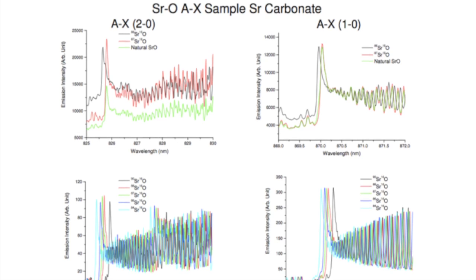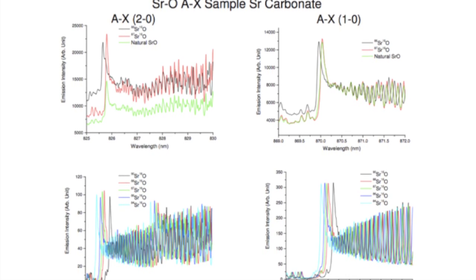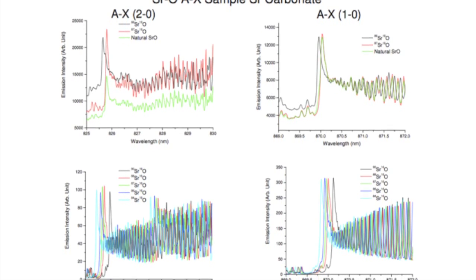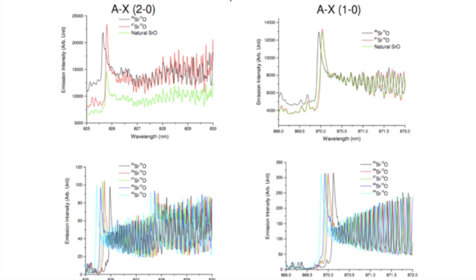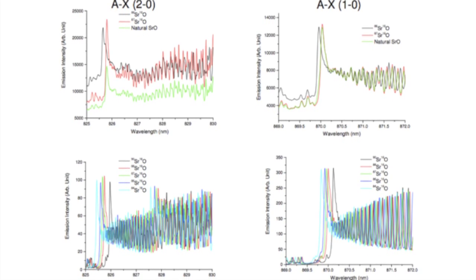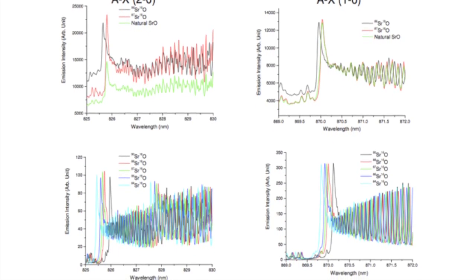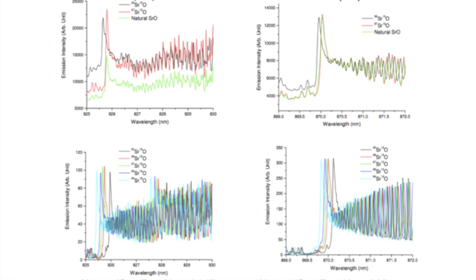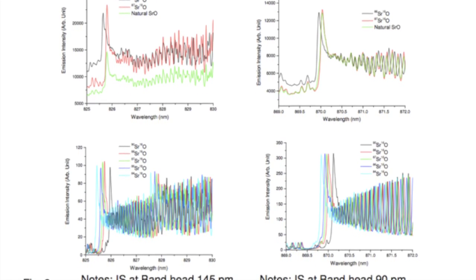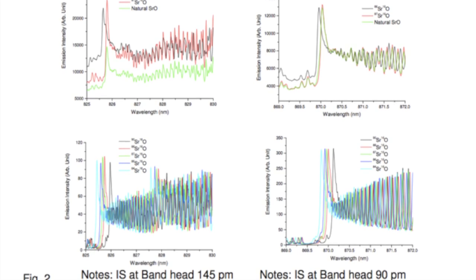Depending on what vibrational band head we're at, this is 825 to 830 nanometers. There should be about a 145 picometer shift between the 86 and 88. And then again, if you're at a different vibrational transition or electronic vibrational transition, you would get a different isotope shift. But again, for strontium itself, it's less than one picometer. So at atmospheric pressure, we can do isotopes now.